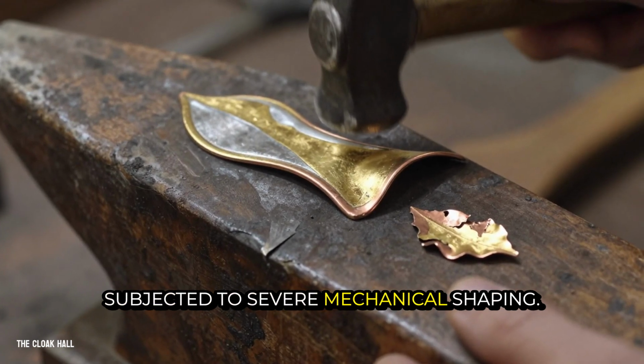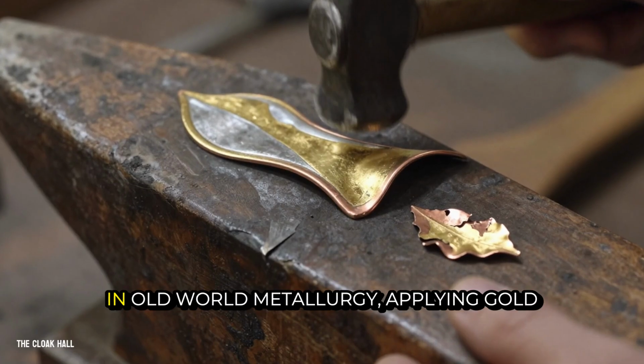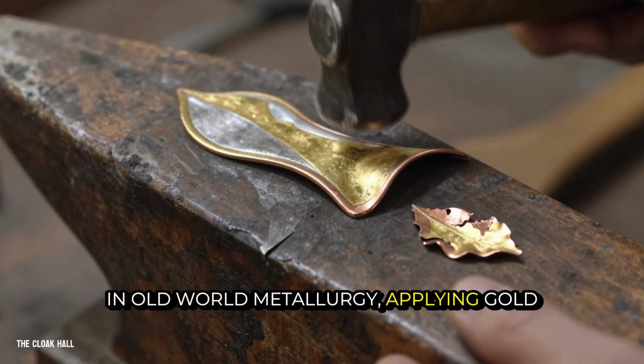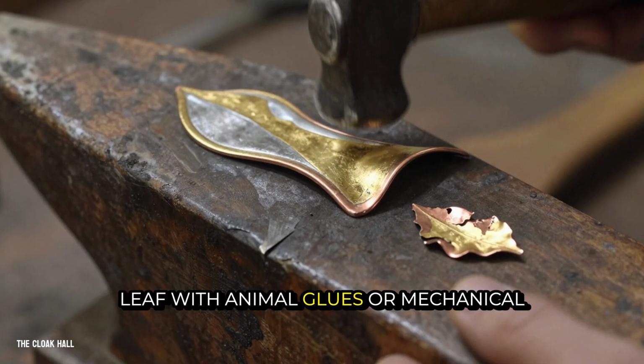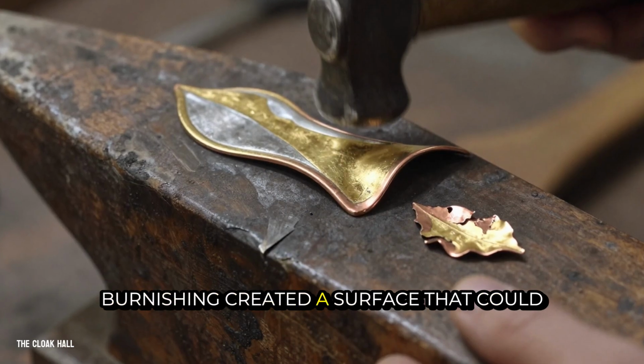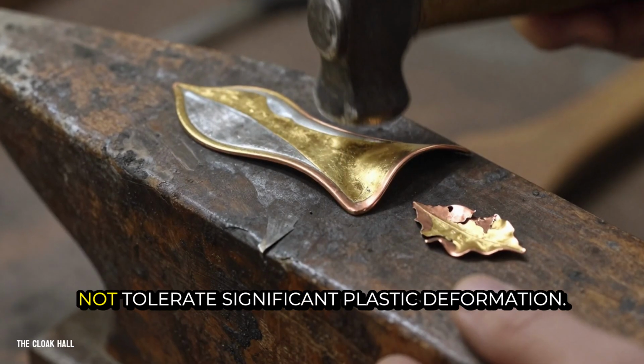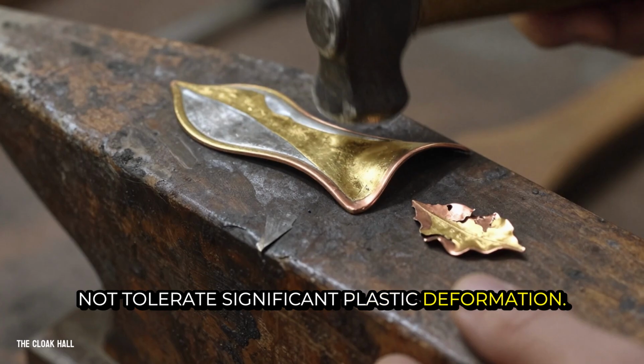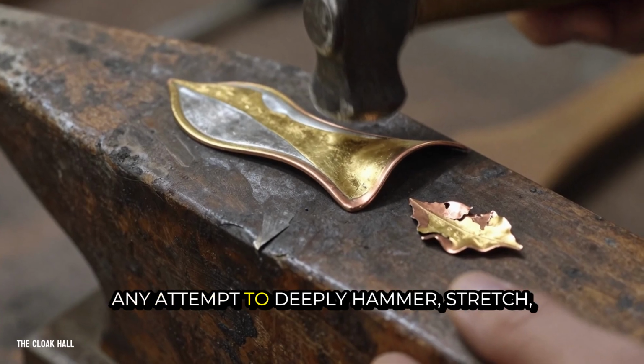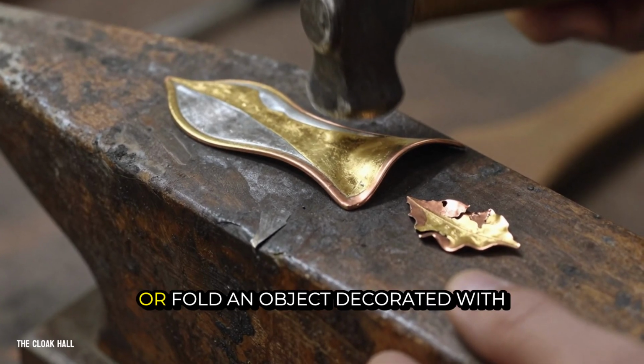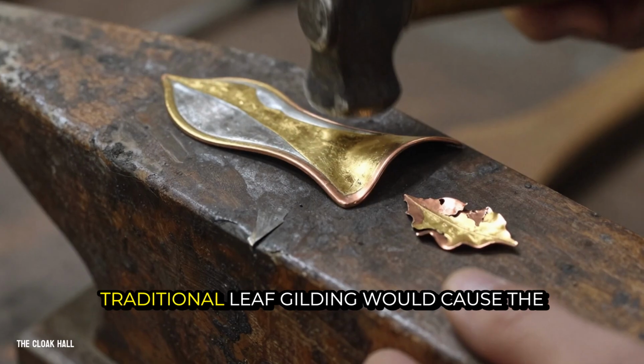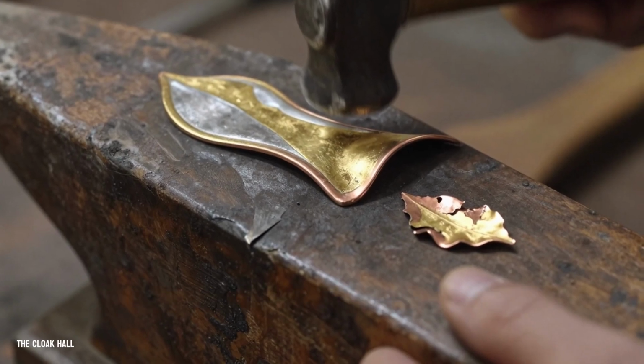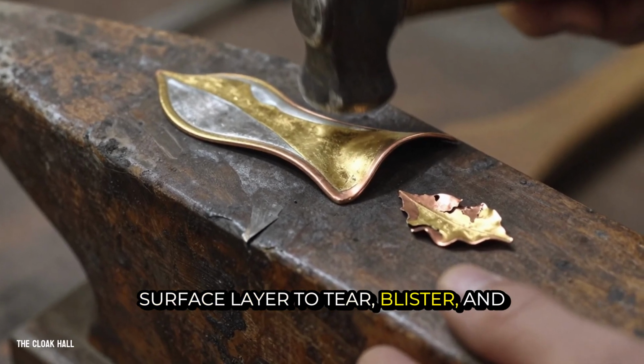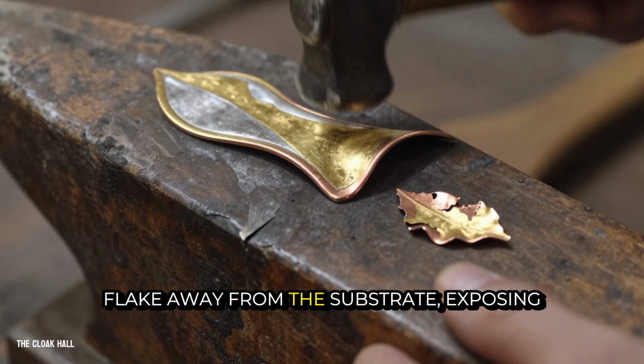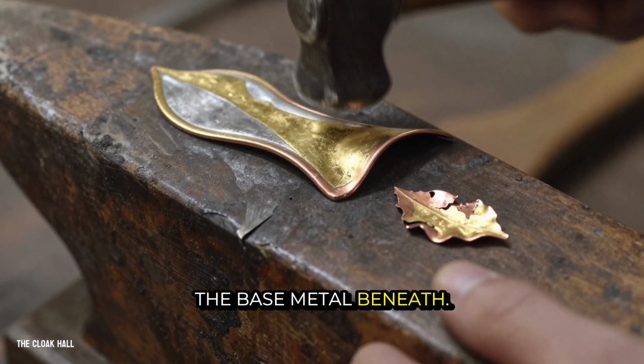to severe mechanical shaping. In Old World metallurgy, applying gold leaf with animal glues or mechanical burnishing created a surface that could not tolerate significant plastic deformation. Any attempt to deeply hammer, stretch, or fold an object decorated with traditional leaf gilding would cause the surface layer to tear, blister, and flake away from the substrate, exposing the base metal beneath.